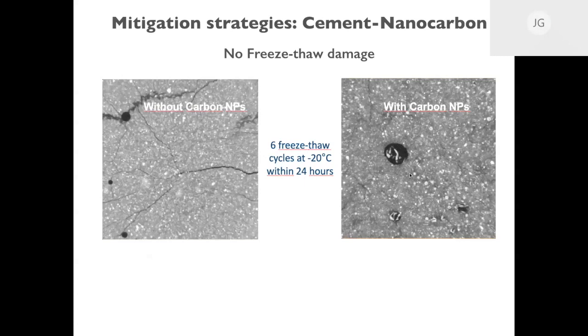I maybe had another question about, you obviously focused on mitigation strategies for freeze thaw, but as you talked about, there's a lot of commonality in the mechanism that's occurring for both freeze thaw and ASR because of what's occurring at the interfaces. Do you see similar opportunities to use some of what you've learned to also mitigate impacts of ASR? Yes, exactly. So we think that, for example, the carbon nanoparticles can help also a lot with alkali-silica reaction, for the reason that the porous carbon has pores where the alkalis can go and stay there. So instead of forming a gel phase in the larger pores, they just stay inside the carbon black.